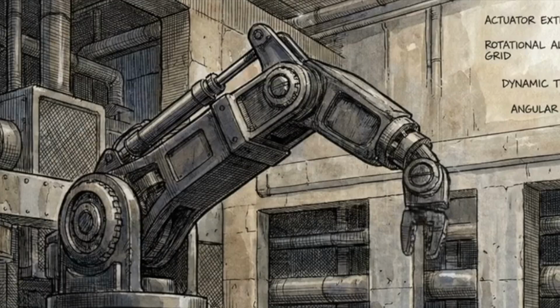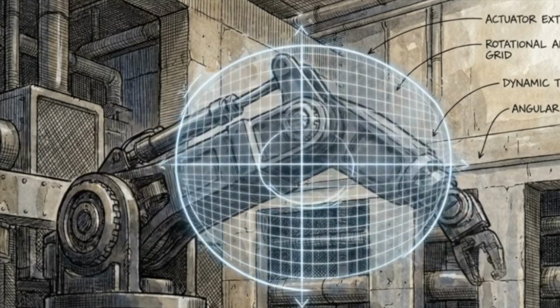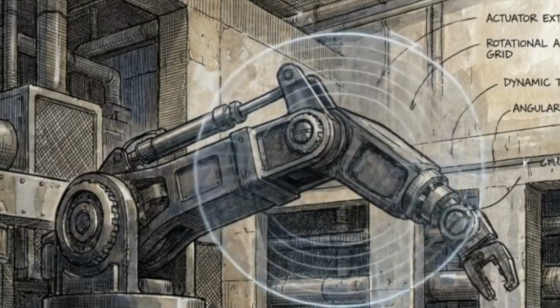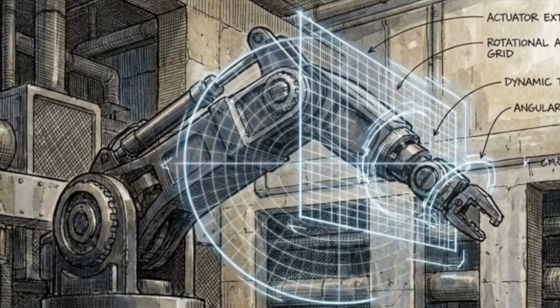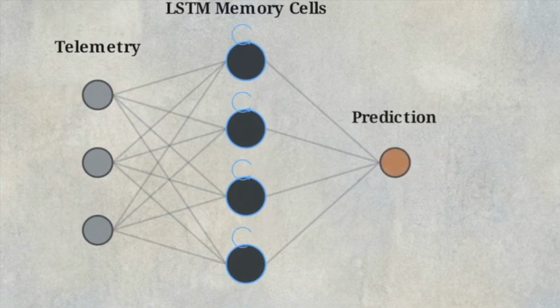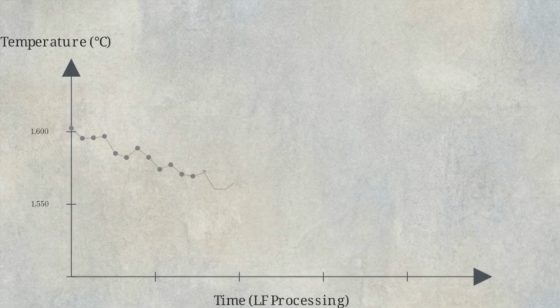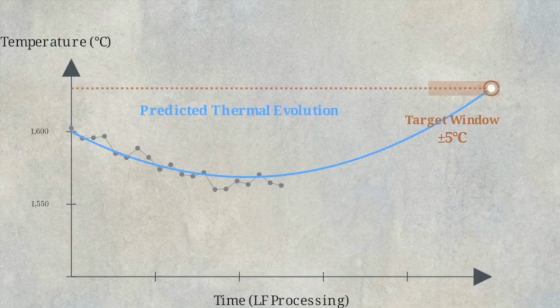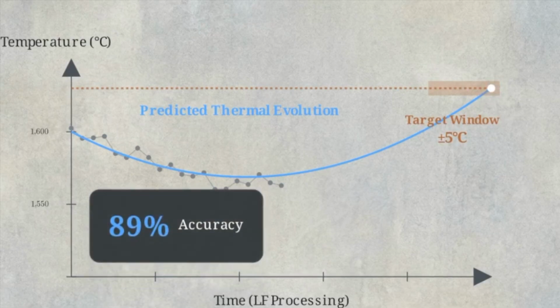The final result is a closed-loop system. It integrates acoustic signatures and process data to drive mechanical actuators. Long short-term memory neural networks use this telemetry to predict the thermal evolution of every heat. This modeling allows operators to hit ladle furnace endpoint temperatures within 5 degrees Celsius 89% of the time.